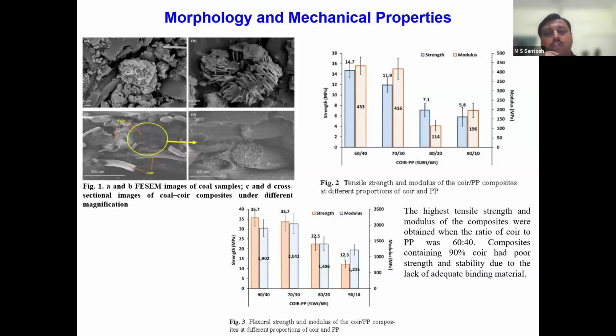And at the same time, we also explored the mechanical properties in terms of tensile strength and flexural strength. As you can see from the two graphs, it is clearly evident that the tensile strength and the modulus of the composites were very good at a ratio of 60:40, because there is a suitable amount of coal, coir, and the blending of the binder material. But as you increase the percentage of the coir to 90%, the binder material composition drastically decreases. And because of this decrease, there is not a sufficient amount of binder for holding the coir materials together, and hence the mechanical strength of the material drastically decreases.